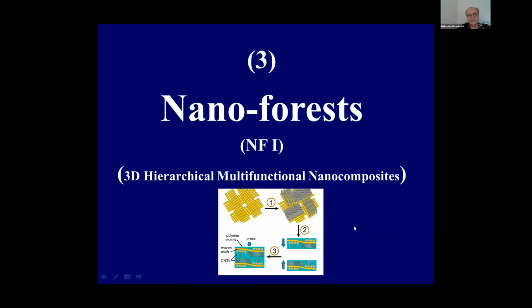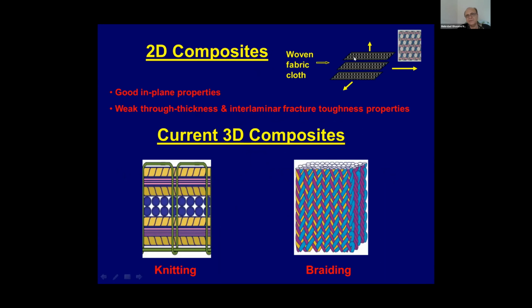So next technology is Nanoforest. Nanoforest is that we grow carbon nanotube on the surface of the fabric, so that way the problem is that if you don't have anything in between the layers, you just have matrix that grows. You don't have fibers. So we grew carbon nanotube in between so that we prevent or delay crack initiation and crack growth. So people have been working with knitting, stitching, and also braiding to solve that problem, but these have associated problems. For example, this knitting increases through the thickness property by 20%, but drops in-plane property by around 15%. So you give some, you take some.